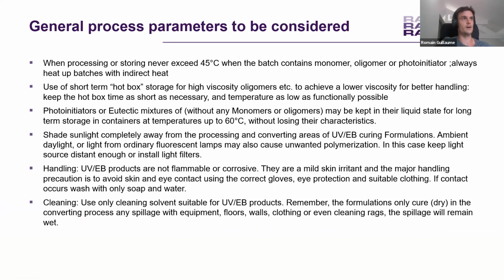Then if we speak about the process parameters that have to be considered, when processing or storing, we should never exceed 45 degrees Celsius when the batch contains monomers, oligomers or photoinitiators. Short-term hotbox storage can be used for high viscosity oligomers in order to achieve a lower viscosity for better handling, if we keep the hotbox times as short as necessary and the temperature as low as functionally possible. Photoinitiators or eutectic mixtures may be kept in their liquid state for long-term storage in containers at temperatures up to 60 degrees without losing any of their characteristics.